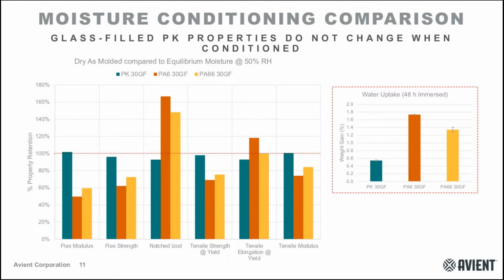And so in this graph, I know there's a lot of bars, a lot of properties located at the bottom, but we're talking about property retention. That dotted red line means 100% property retention if we're looking at a dry as molded sample compared to an equilibrium moisture conditioned sample. So if a bar is near 100% on this graph, it means that the property doesn't change all that much. And what you see broadly in this graph is that glass-filled aliphatic polyketone does not change its properties all that much when you're comparing dry as molded to moisture conditioned, whereas nylon 6 and 6/6 do noticeably change.